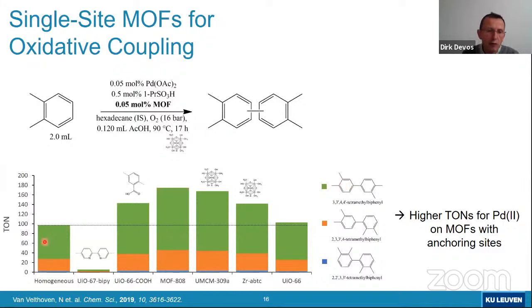And we compared a homogeneous system, and you see the conditions enumerated here. I'm not going to go into these details. We compared the homogeneous system with what we got when we added the palladium with a MOF to this system. And then remarkably, we observed that there were quite some MOFs like this MOF-808, but also some other zirconium-based MOFs like this carboxylic functionalized UiO-66, which all had a beneficial effect on the turnover number in these palladium couplings. So for instance, if the homogeneous catalyst would do something like 100 turnovers, you would go well over that if the palladium was sitting on a MOF like MOF-808.